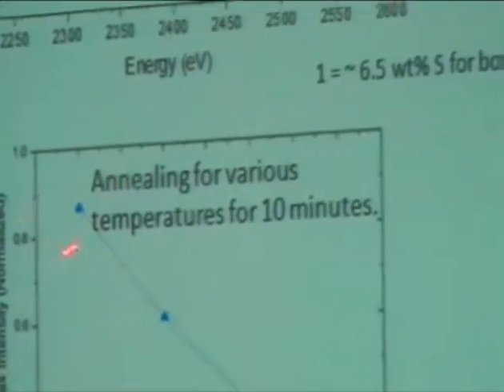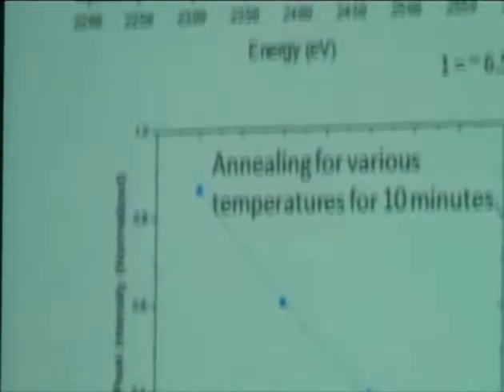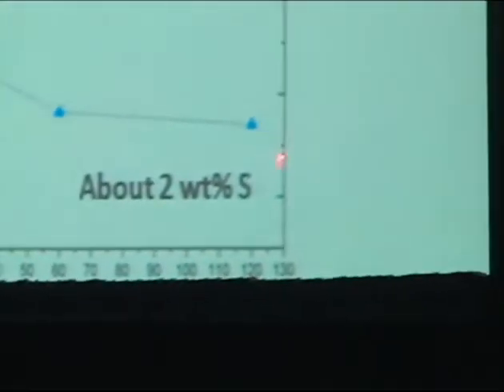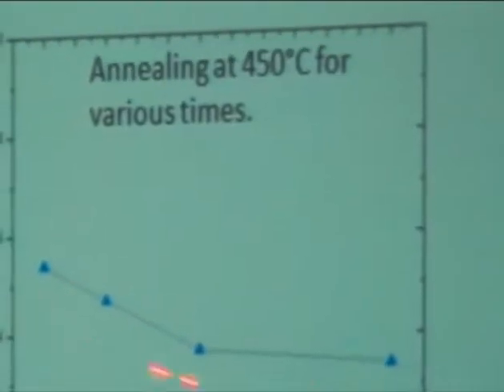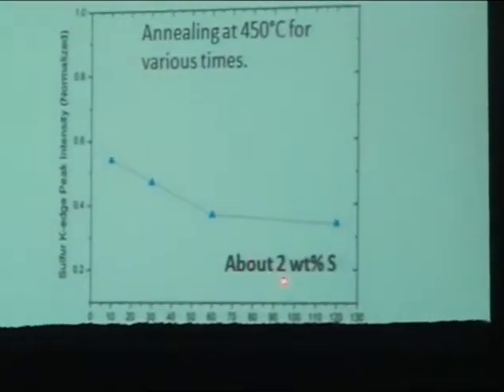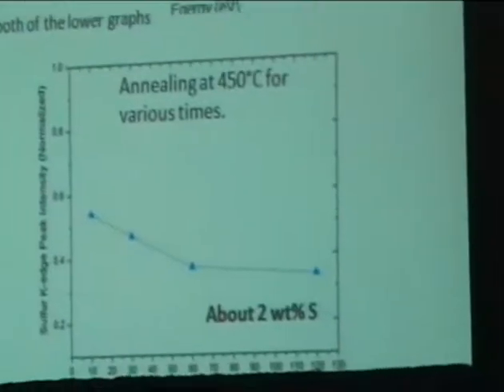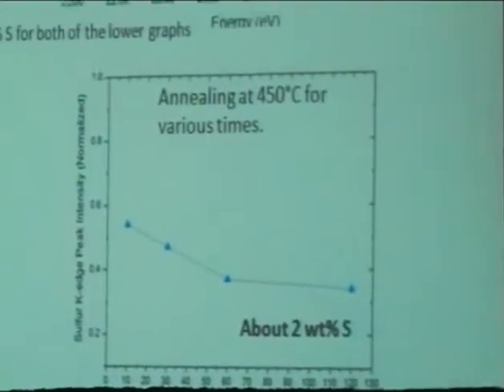It goes from something of the order of about 7 weight percent down to about 0.7 weight percent. Over here, we're doing a time study at that 450, which you will be able to read: 10, 30, 60, and 120 minutes. And so as synthesized, we end up with materials that are about 2 weight percent sulfur. The commercial sample that we're comparing it to is 2.5 weight percent. So they're the same order of magnitude with respect to sulfur. I think I'm going to skip this one in the interest of time and go to this one.